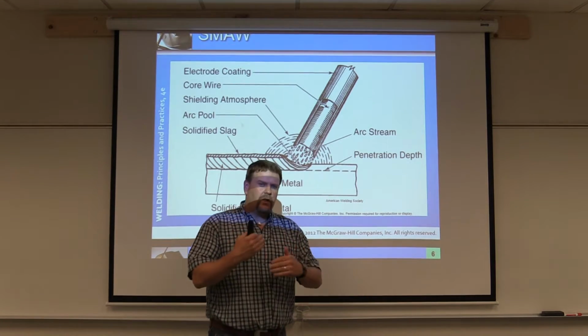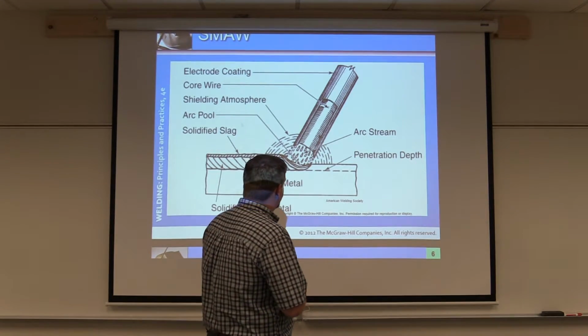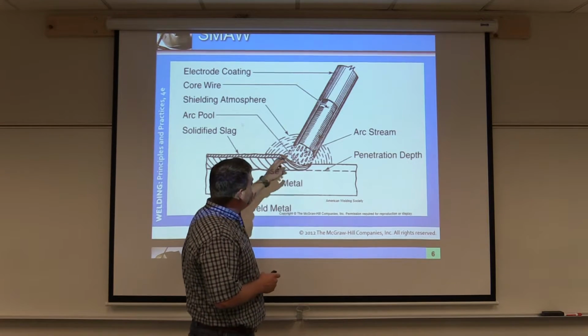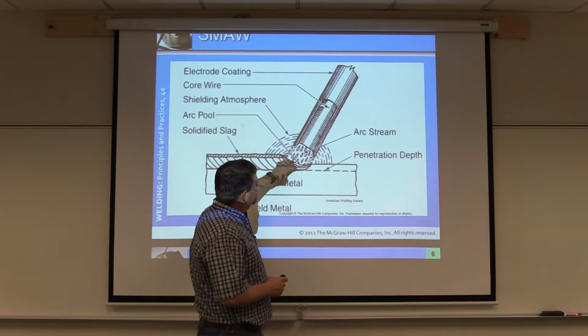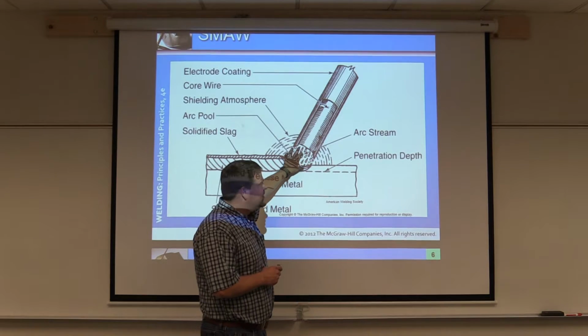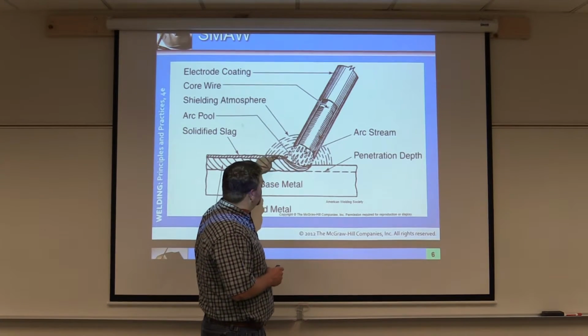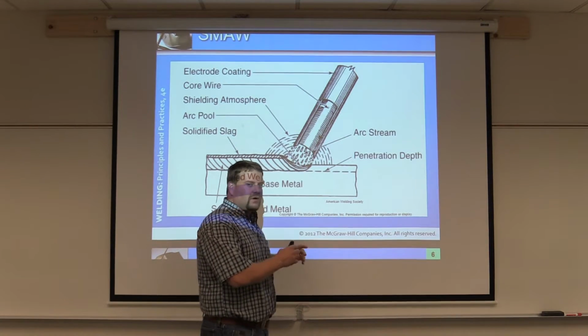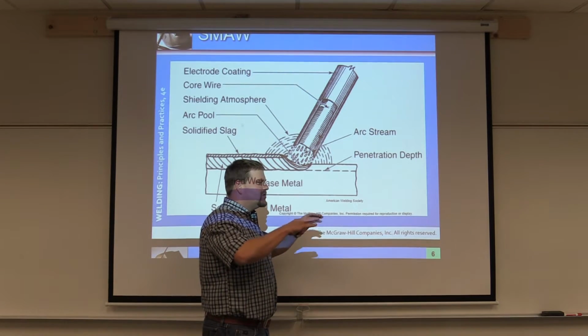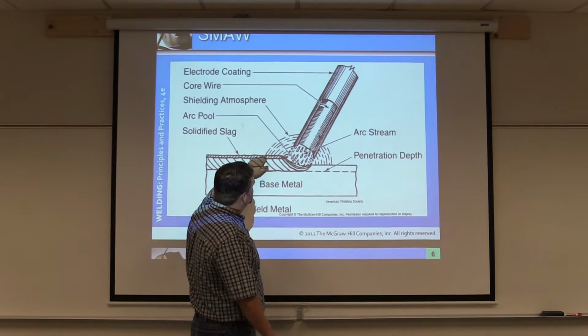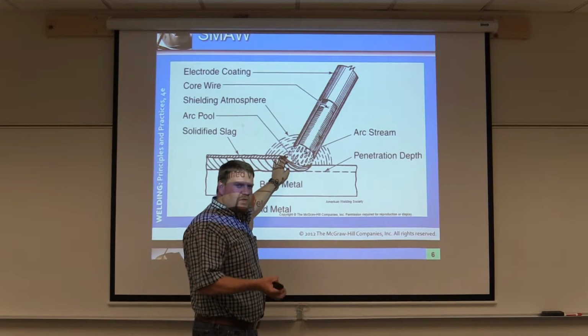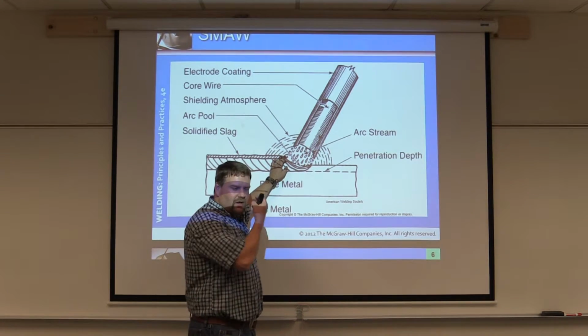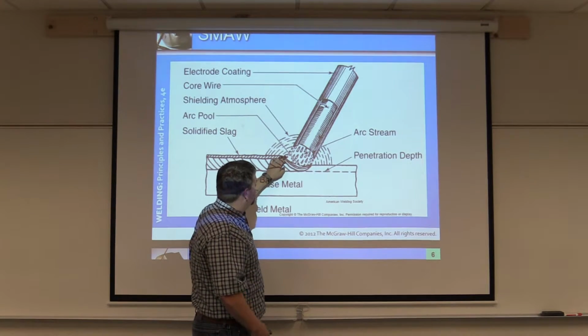We'll talk more about the metallurgical standards going through the program later on. But I wanted to just discuss, this is when most of the alloying takes place. It's not on the slag. That flux is absorbed into that weld puddle at 9,000 degrees, and it spreads out evenly and disperses, and then all of a sudden it solidifies together, and then that's when the slag brings all the impurities, or kind of the garbage, so to say, to the top, the things that the weld pool rejects, that doesn't bond to the metal.